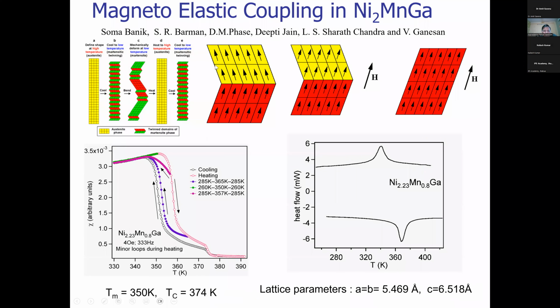So in magnetic force microscopy, what happened? If you apply a field at some particular position, there is a para to ferromagnetic transition. If there are spins, they are all arranged in one direction in the ferromagnet, and another domain will be arranged in another direction. If you now apply a magnetic field, what will happen? Normally only the magnetic spins will change, in the direction of the applied field. But here you see that the whole yellow material changes direction. It is not only the spins that are changing; the whole mechanical alignment, a whole mechanical transformation, takes place and they all arrange. So by magnetism, you can change the material's mechanical property. This is very interesting. Okay.